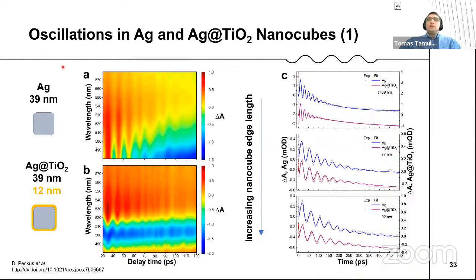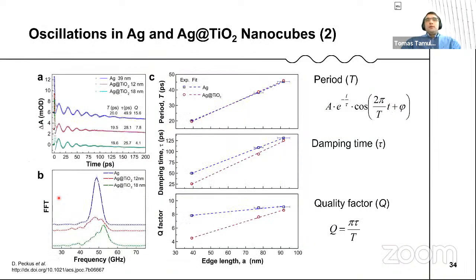And it scales with dimension, and you can see the shift in position if you have this titania, because the resonance shifts to a different side of the spectrum. And it has a linear dependence of this period on the edge length and the Q factor, the quality of this oscillation, and on the damping time that is used to fit those equations.